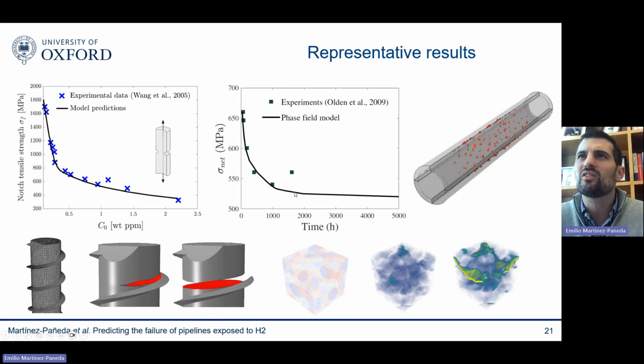And you can see here, let me run this video. You can see here a very complicated problem. We have a pipe containing hundreds of defects due to pitting corrosion. And we can introduce those defects into the model, and we can see how those defects are growing. And then eventually, as you can see here, how you get the coalescence of multiple defects and the complete failure of the vessel. So no matter how complicated your problem is, whether it's small, whether it's large, the model can handle it. And it can do so, showing, again, a very good agreement with experiments.